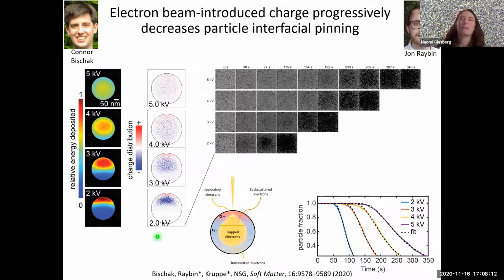And actually, there's something like a 20-fold more accumulated charge at these lower accelerating voltages because the electrons don't make their way through the entire diameter of the particle like they do at the higher accelerating voltages. So essentially, with these experiments, by varying the accelerating voltage, we were able to vary the accumulated charging rate, and making that connection enabled us to specify the effect of progressive electron beam exposure as a function of time at a given accelerating voltage, this being the series that I've been focusing on primarily here at 5 keV.